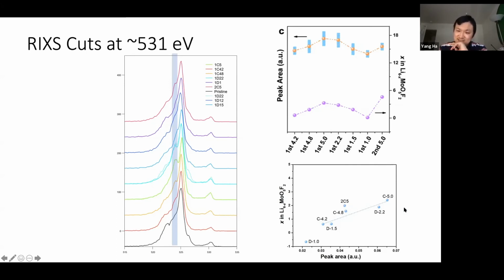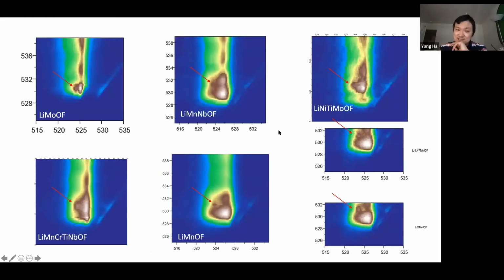And what's even better is we have measured tons of samples. No matter what type of cations we have, as long as we have oxidized oxygen, we will have this oxidized oxygen feature. It doesn't matter if you have manganese or nickel or a high entropy material. So we really call this the fingerprint of the oxidized oxygen. And it's now the slam dunk technique in the field of batteries to see if there is any oxidized oxygen cycled in your electrode.